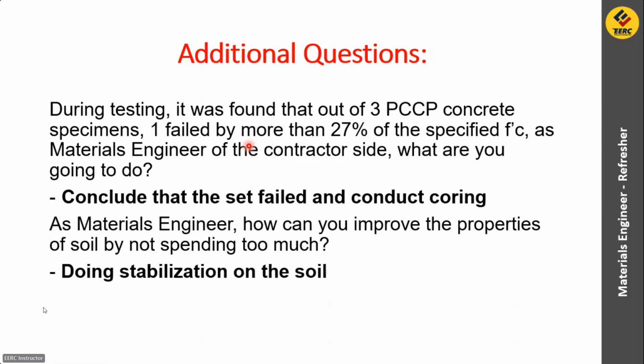So next, during testing, it was found that out of 3 PCCP concrete specimens, 1 failed by more than 27% of the specified f'c. As a materials engineer of the contractor side, what are you going to do? So more than 27% na siya, no? So therefore, the set failed and conduct coring. Okay, to include that the set failed and conduct coring. So meron naman tayong criteria na na-discuss. So balikan nyo na lang din.